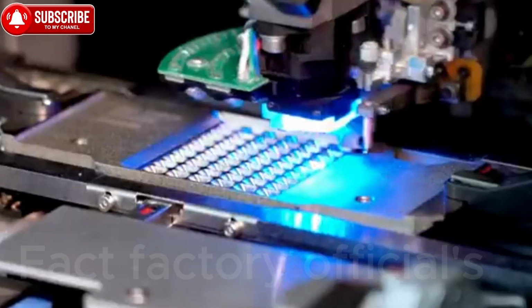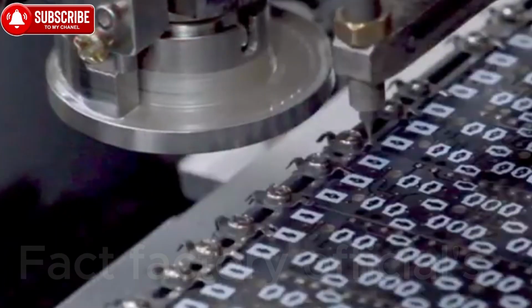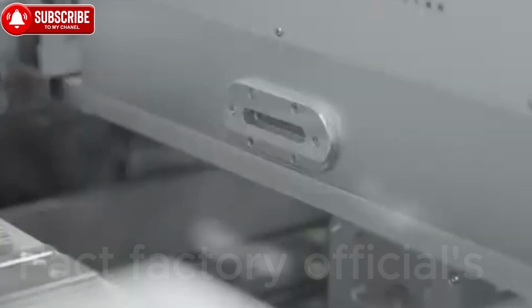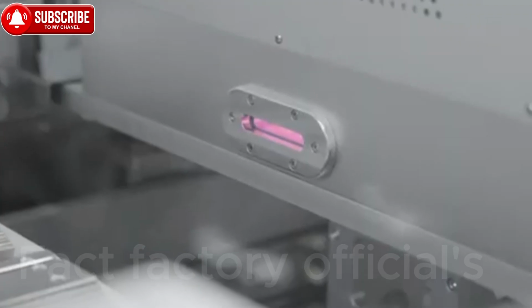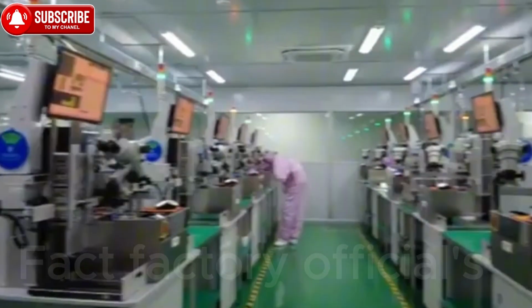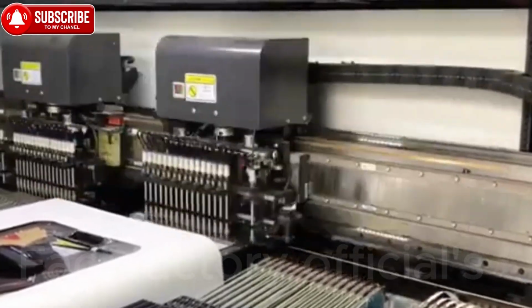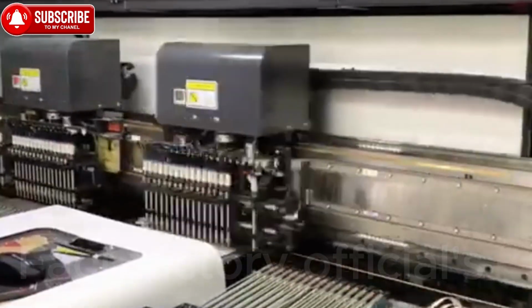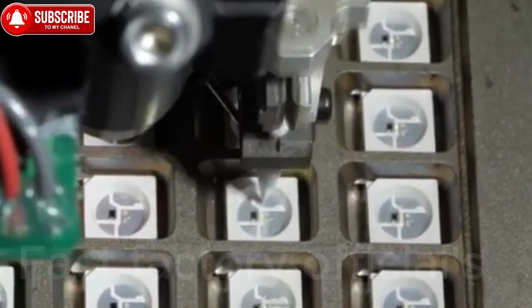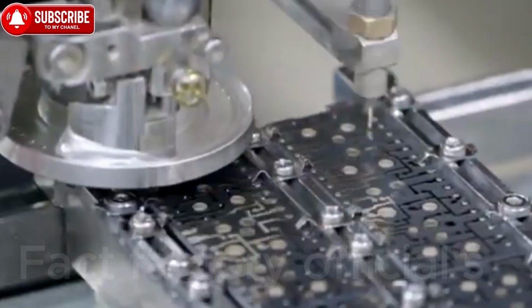A misalignment of just 20 to 30 micrometers can cause color shift, reduce the LED's lifespan, or even lead to immediate failure in the next processing step. For this reason, once an entire strip of chips has been placed, the lead frames are transferred into a thermal curing oven. There, a stable temperature is maintained for minutes, allowing the adhesive to fully cure and permanently lock each chip into position as a unified structure.